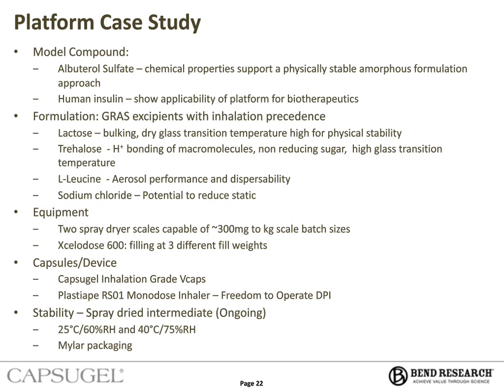The equipment, we talked about two different spray dryer scales from milligram to kilo type batch sizes. The Xcelodose 600 for filling. The capsule device combination were Capsugel inhalation grade V-Caps, and the device is a Plastiape RS01 monodose inhaler, so an off-the-shelf, well-known DPI. And stability, which is ongoing. Of course, everyone wants to ensure that the powder remains physically stable and maintains its aerosol performance. So at the moment, we only have 1 month data, but stay tuned for the additional analysis in the future.